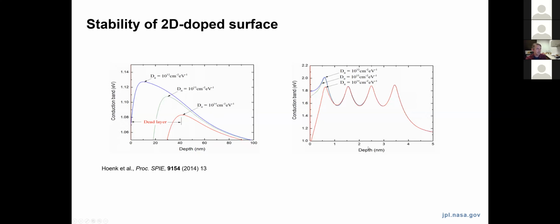With a delta layer, you can see that the x-axis has changed a lot on these plots. Now, variations in that interface state density have little effect on the conduction band profile, even a nanometer away from the surface. I'm showing here several delta layers, and this is the approach that we've taken in more recent years. A single delta layer is often sufficient to achieve the improvements in efficiency that we're looking for, but multiple delta layers can help with this stability issue and help increase the conductivity of this modified back layer. So this is what we've been referring to as 2D doping or superlattice doping for multiple delta layers.